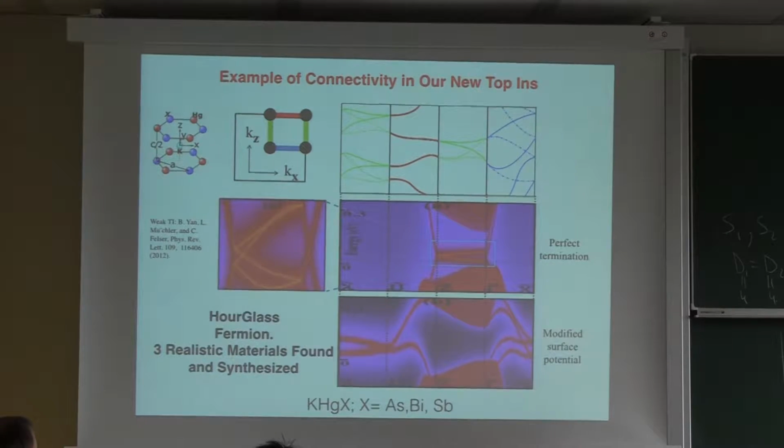Now, these are the two manifolds, S1 and S2. These are the high symmetry lines. And now notice that there's another manifold, the red one, where bands come in doubly degenerate, and I'll explain why. This is twofold degeneracy, and the criterion says that this has to divide this, and it does. And if this divides this, then I can draw the following surface band structure. Just look at this side of the surface, just this triangle. This is another. This can vary. I can have more than one choice here.